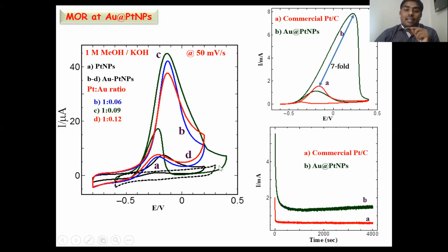And we have compared the synthesized bimetallic nanoparticles with the commercial one. The commercial one shows the methanol oxidation with only 2 milliampere current, and the synthesized Au platinum bimetallic nanoparticles exhibited higher catalytic activity by showing an enhanced oxidation current, a 7-fold increase, and also confirmed that the Au platinum bimetallic nanoparticles synthesized in this method exhibited higher catalytic activity than the commercial platinum catalyst. It is also proved from the chronoamperometric studies.